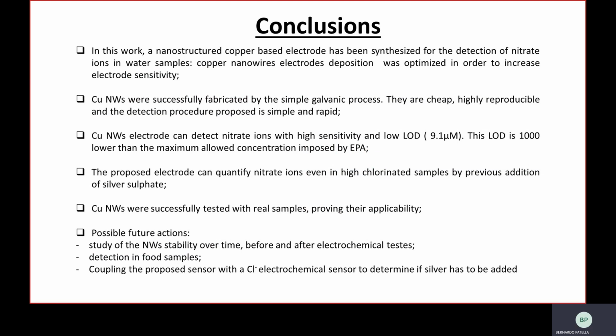The nanowires electrode can detect nitrate ions with high sensitivity and low limit of detection, and the limit of detection is almost 1,000 times lower than the maximum allowed concentration imposed by the Environmental Protection Agency. The proposed electrode can quantify nitrate ions even in highly chlorinated samples by previous addition of silver sulfate.